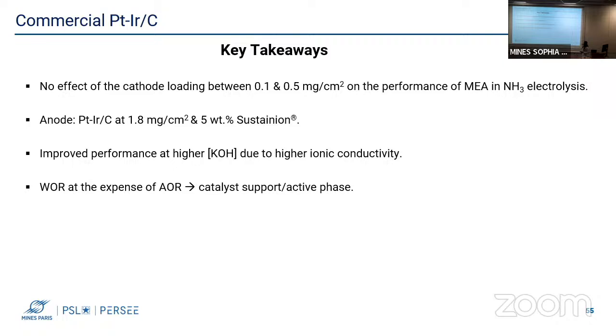Improved performance was obtained at the higher electrolyte concentration due to the improved ionic conductivity, and the water oxidation reaction is proceeding at the expense of the ammonia oxidation reaction, which means possibly we should either work on the catalyst support or the active phase. For the rest of the time, we chose to work on the active phase and we prepare our own homemade catalysts.